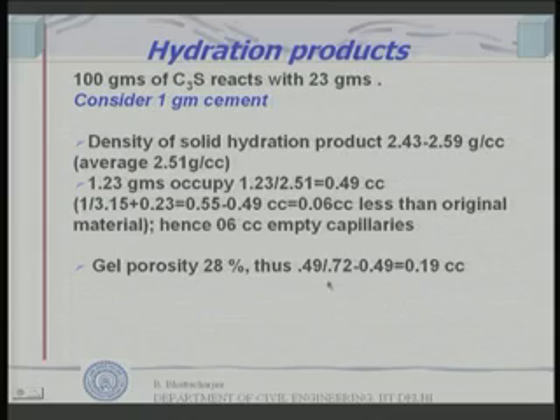0.49 divided by 0.72 minus 0.49, because 0.72 is the volume occupied by the solid, the total will occupy 0.49 divided by 0.72, that is 0.68, minus 0.49 gives you about 0.19 cc. So the volume of gel pores should be 0.19 cc. By simple calculations one can see that 0.19 cc of gel pores will always be there. So you have 0.49 cc of gel solid in your earlier diagram, and 0.19 cc of gel pores, if you have taken 1 gram of cement.